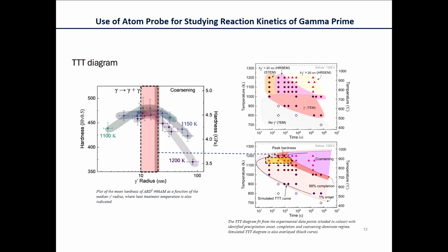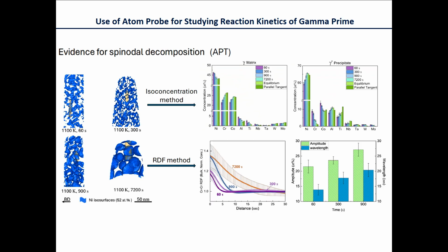We've been using this kind of technology for studying the reaction kinetics of the superalloys by the so-called time-temperature transformation diagrams. This is the work of Yuhan Zhuge in my lab, and he will present at the European Superalloys Conference these TTT diagrams here, where he's trying to understand the mechanism of transformation for this reaction. And you can see here with the three-dimensional atom probe maps, he's able to show that the amplitude and wavelength associated with the decomposition reaction appears to be consistent with the spinodal type of phenomenon.